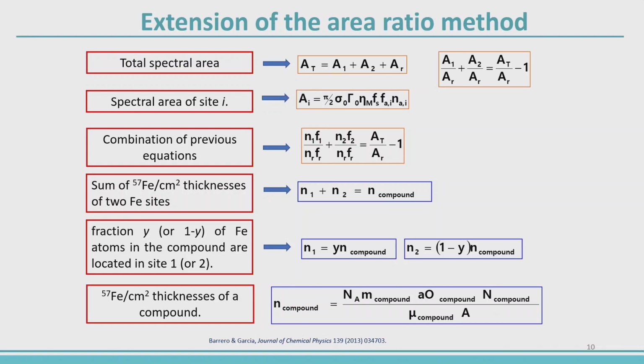Using the expression for the thin absorber approximation, we just use this formula and replace it in the previous equation, and we get this. It's very simple. These are the things that change from sample to sample, from ferrite to ferrite. This is very important. We have to take into consideration the formula that we have for the specific ferrite, because we have to know the fraction of the iron ions located in each site. So this is general, but it depends on the sample. You will notice later, when I show the formulas for different ferrites, how it varies from ferrite to ferrite, because this is the starting point here.